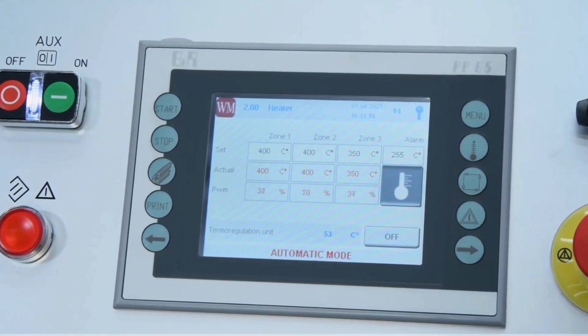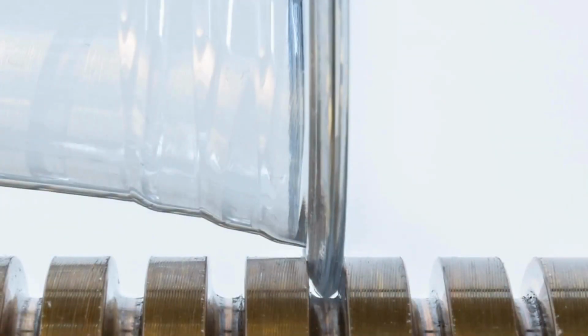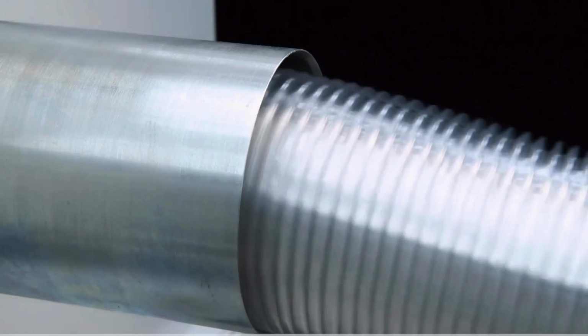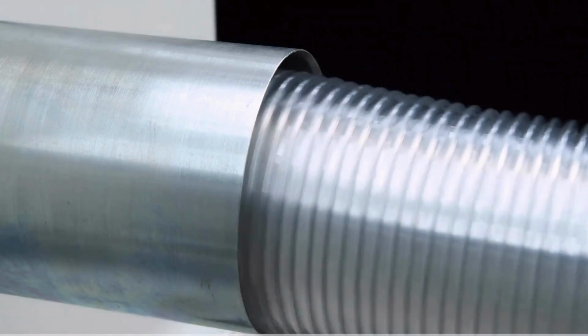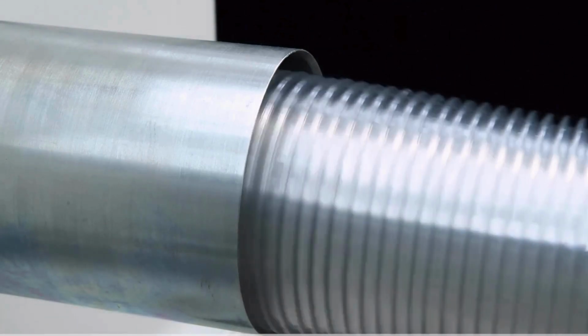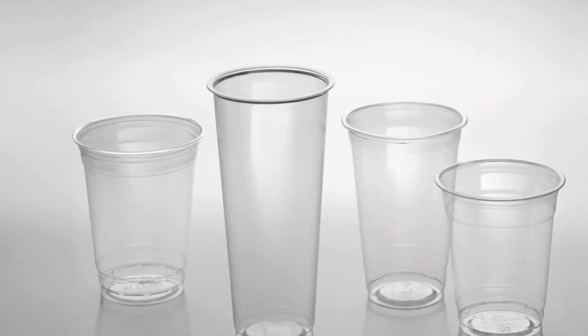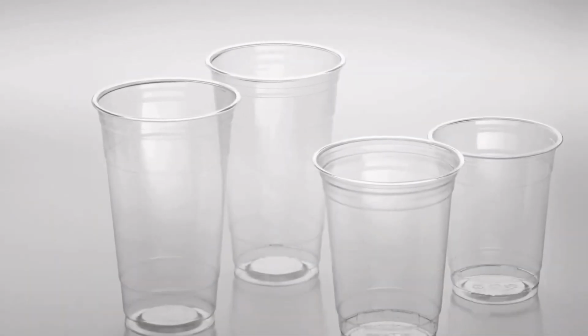At this temperature, the polymer's elastic modulus drops sharply, allowing it to bend without cracking. If the rim is too cool, it becomes brittle and can develop tiny fractures called crazing. These create the white, chalky edges known as stress whitening. But if the heating is right, the polymer chains can move and realign, giving a clear, smooth, and durable rim.